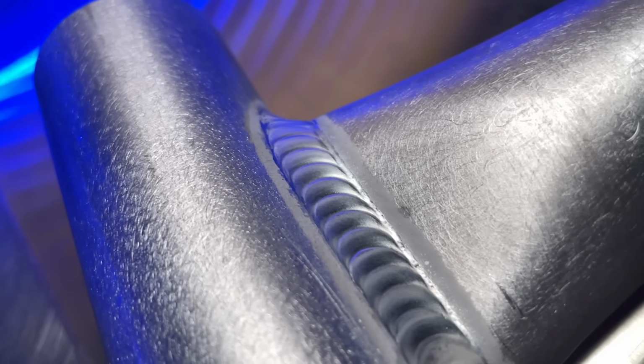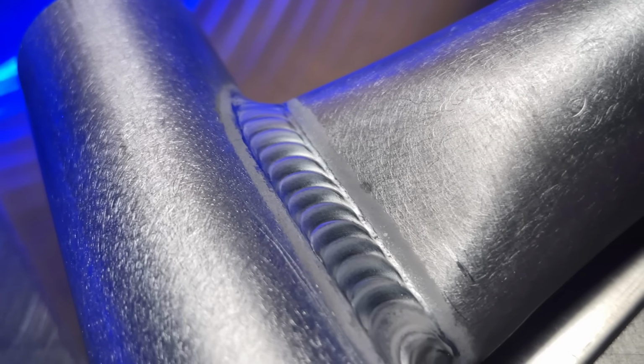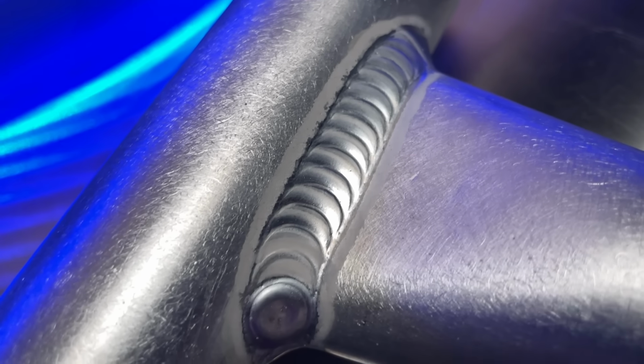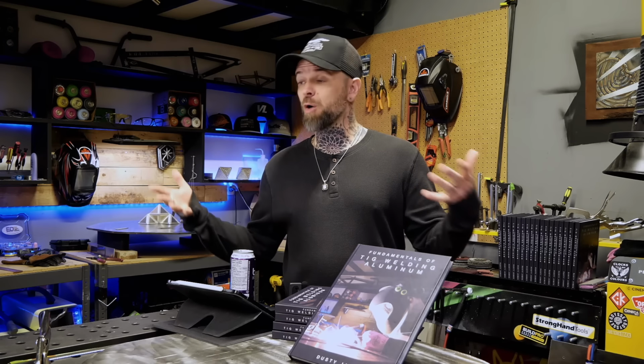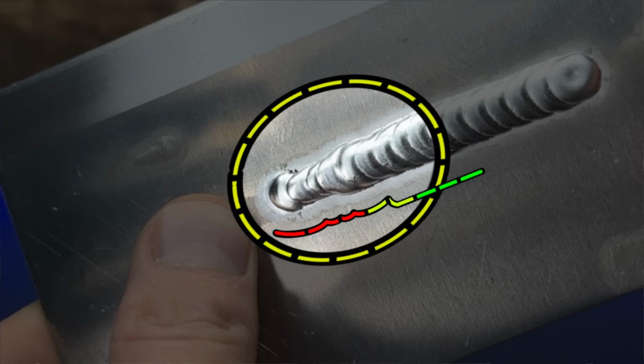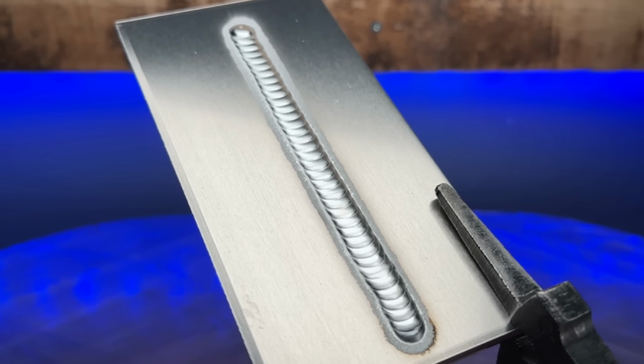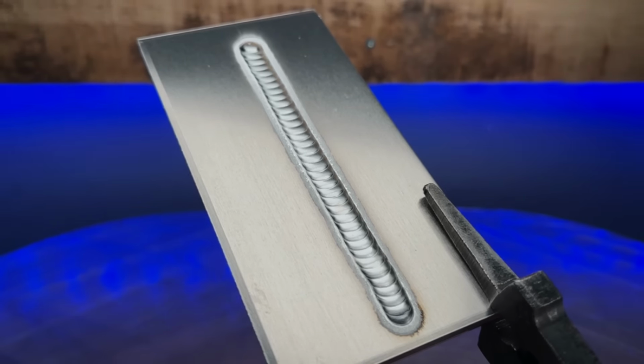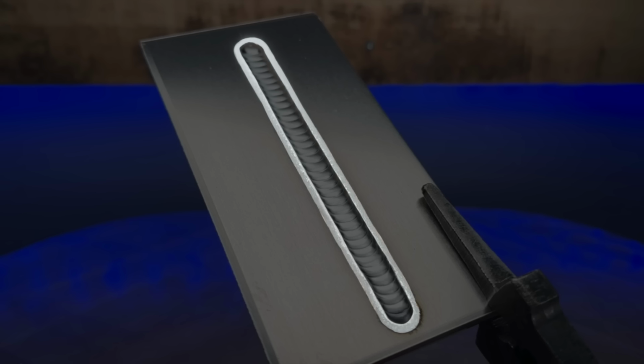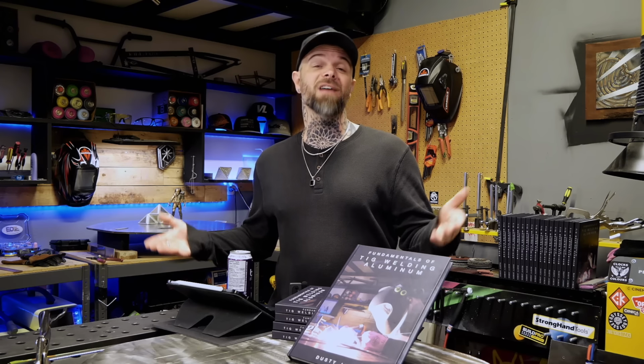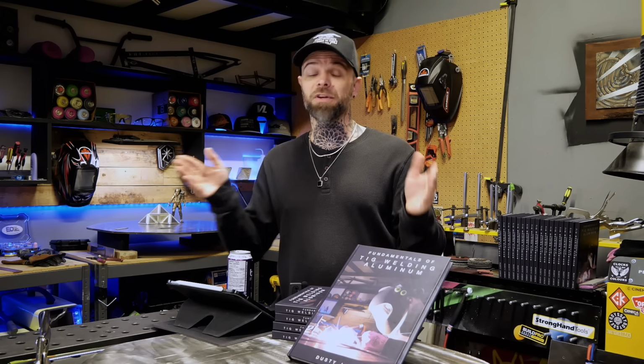The cleaning action is a dead giveaway for how somebody did with the balance between heat and filler. If this balance gets out of balance, you can see that the edges of the welding pass will not have proper fusion and the cleaning action looks bad. Looking at this one where we have a good, smooth, blended edge, take a look at how consistent and smooth the cleaning action is. Right on. This is an indication that you have this balance done perfectly. Well done. Clap, clap, clap.